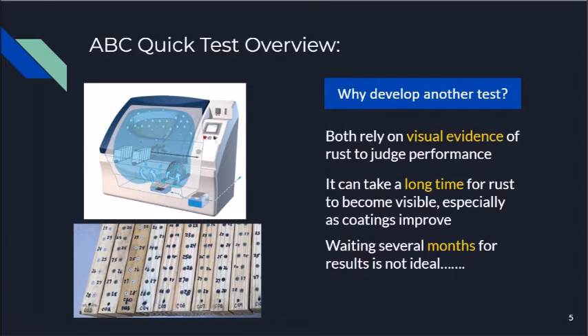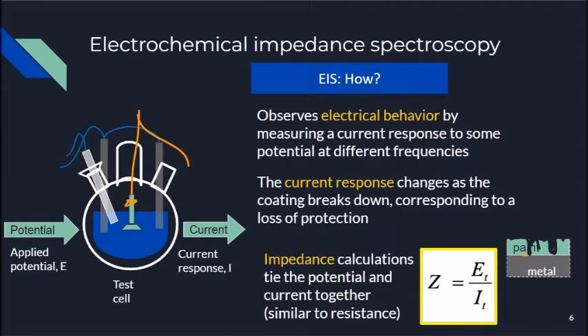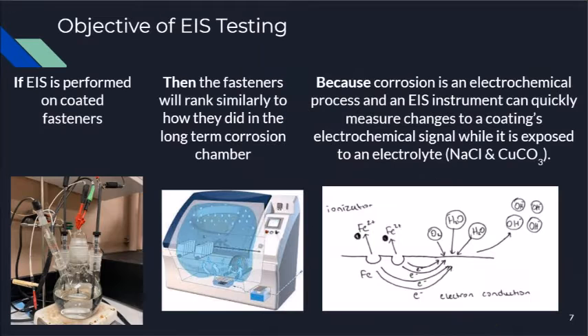Both of these tests rely on visual evidence of rust to judge performance, but it can take a long time for rust to become visible, especially as coatings improve with time. As you can imagine, waiting several months for results is not ideal, which is why a screening test may be useful. Electrochemical impedance spectroscopy observes electrical behavior by measuring a current response to some potential at different frequencies. The current response changes as the coating breaks down, corresponding to a loss of protection. Then impedance calculations tie in the potential and current in a way that is similar to resistance.